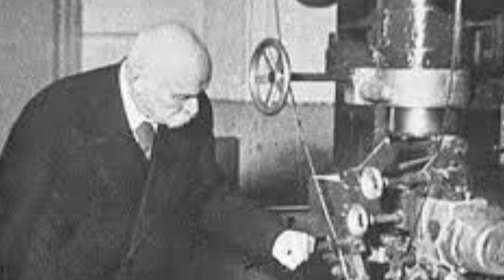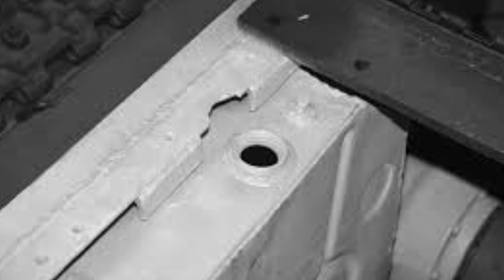The seams looked different from manual welds, wider, with a distinctive rippled appearance from the automatic travel, but the metallurgical testing showed they were actually superior. The heat-affected zone was narrower because of the faster travel speed. The penetration was more consistent because the arc length never varied. And most surprisingly, the quality was so consistent that the rejection rate dropped from 30% to less than 5%.